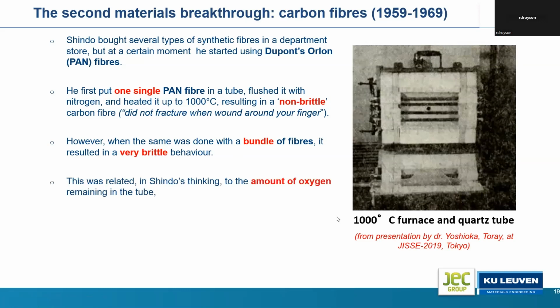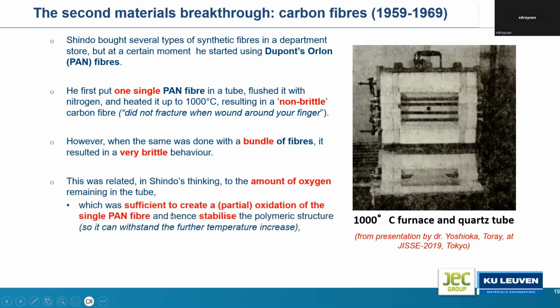And in his thinking, it could be related to the amount of oxygen remaining in the tube which he flushed with nitrogen. That amount of oxygen might have been sufficient to create a partial oxidation of the single PAN fiber, and hence to stabilize it, because oxidation of polyacrylonitrile fibers results in a thermal stabilization, so the fiber becomes heat resistant so that it can withstand higher temperatures for the carbonization, whereas there was not enough oxygen available for oxidizing all the PAN fibers in a bundle of fibers. And hence he discovered that the oxidation process is the critical step in the production of carbon fibers.